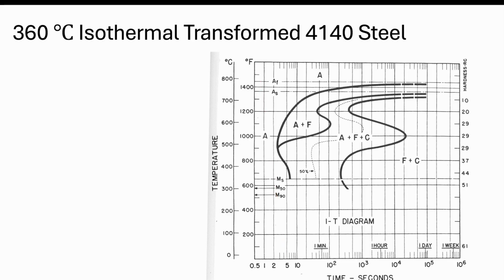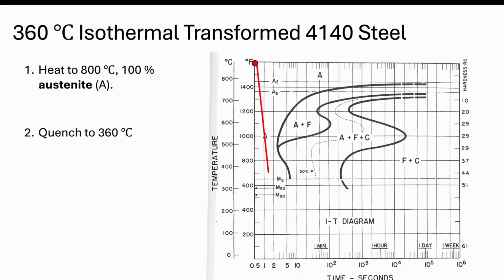So let's go from the quenched and start going up in temperature for our isothermal transformation. In this one, I'm going to look at what happens if we do this isothermal transformation at 360 Celsius. 360 is somewhere around here. The steps are the same. I start and I heat above 800. I make sure I have 100% austenite. I rapidly cool to my temperature, in this case 360, about right here. And then this is where my isothermal transformation comes in. If you look at the axis here, this is time, this is temperature. So essentially, how much time are we going to spend at the isothermal, or constant, temperature?